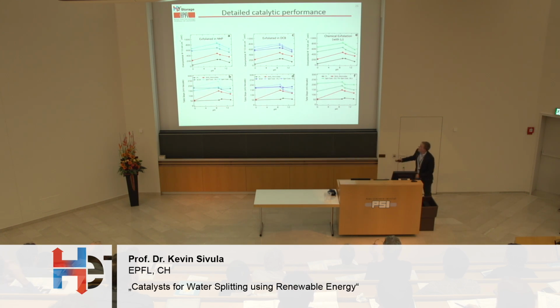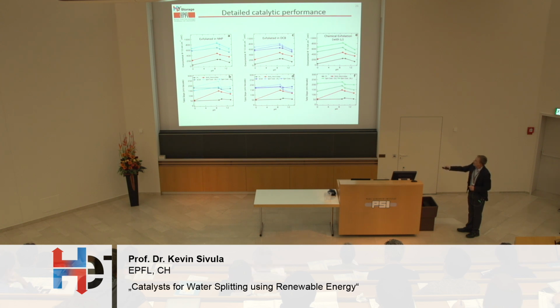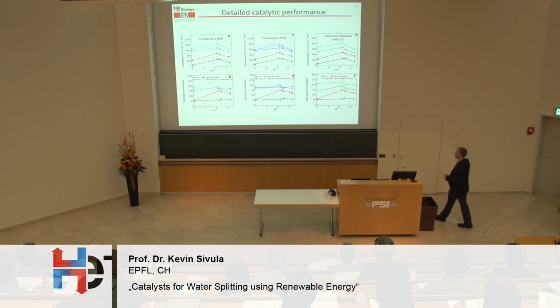We look at, in detail, both the overpotential and the Tafel slope for these different types of molybdenum sulfide that we've made. And there's a lot of data here, and I don't have time to go through all of it, but the important thing to note is that for the electrodeposited sample, which is in red, it performs very well, very close to platinum under acidic conditions, but further away in basic conditions. However, our solution-processed samples actually perform closer to the electrodeposited sample in basic conditions, which suggests that perhaps our materials would be more useful for this alkaline electrolysis, but we have to investigate more the long-term stability of them in the basic conditions. But it begs the question, what's the difference between the performance of these three different samples: exfoliated in the NMP solvent, exfoliated in the DCB, and also this lithium-type exfoliated sample?